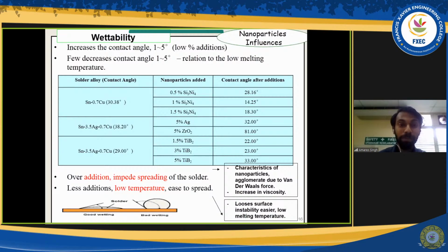So let's see what happens when we add nanoparticles. Here we could see that a small addition of nanoparticles, for example, we add 5% of argentum, it tends to reduce the contact angle to 32 from 38. But then when we add 5% of zirconia, it seems to increase the contact angle further.